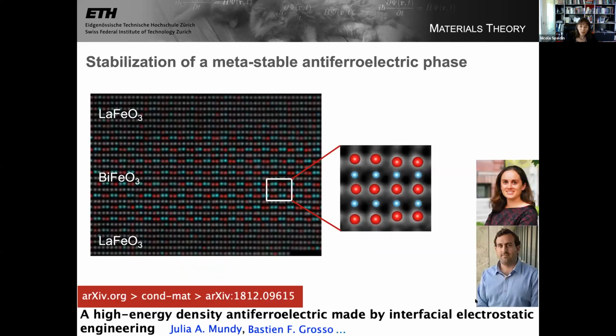Okay, so this is work that was done by Julia Mundy, who's now an assistant professor at Harvard University, and Bastien Grosso, who's a PhD student in my group, who did the density functional calculations. And here's another high resolution transmission electron micrograph of a film that Giulia grew, which was made of lanthanum ferrite. So lanthanum ferrite is not a ferroelectric, it's a non-polar material. Then bismuth ferrite, the material we've been discussing, and then lanthanum ferrite again.